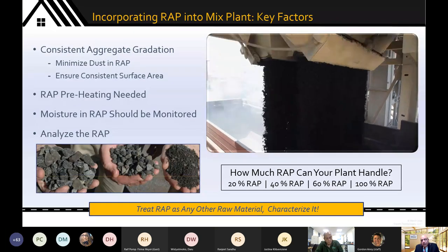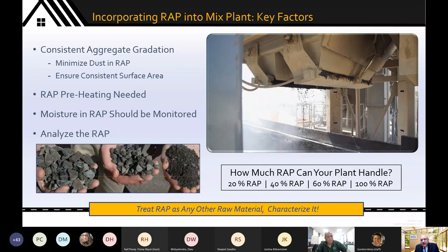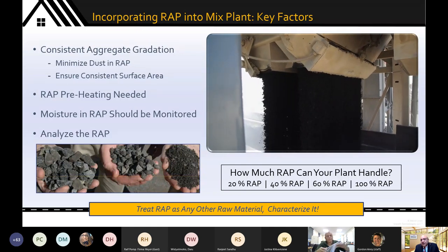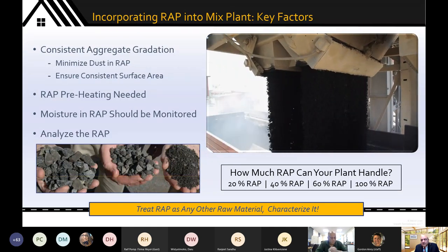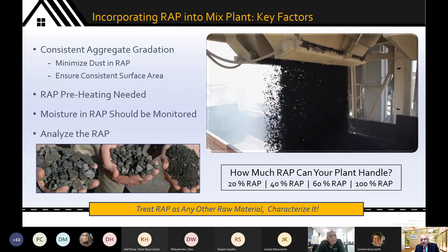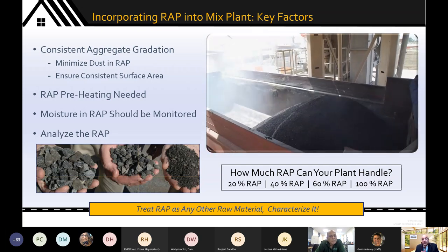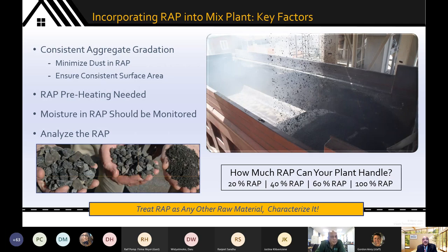So as I mentioned before, treat RAP like any input material into your process. If you simply look at it as garbage, well, garbage in, garbage out. So you do need to have a consistent gradation. This step is important. You need to minimize the fines in the RAP, the dust in the RAP, because they basically act as sinks for bitumen absorption.